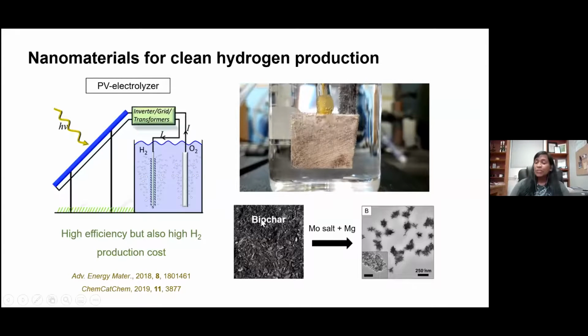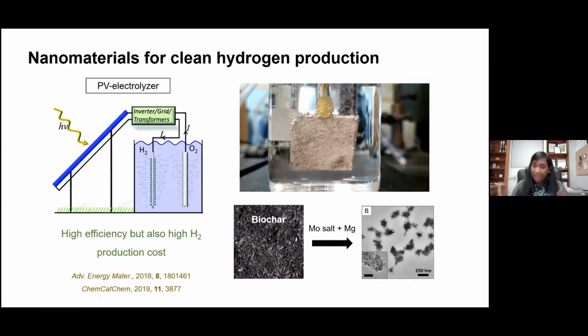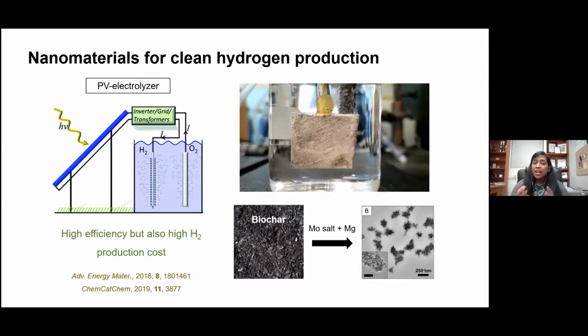So her group actually makes this biochar, and we then take this biochar and mix it with molybdenum salt and magnesium. And then we get a catalyst known as molybdenum carbide, which almost looks like a sea urchin. And this particular catalyst is porous. It has very, very high surface area. It's on the nanoscale, and it actually performs as well as platinum when it comes to making hydrogen through water splitting. So this has been a very exciting result.